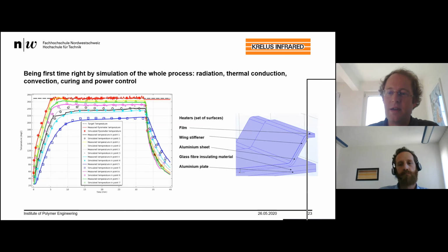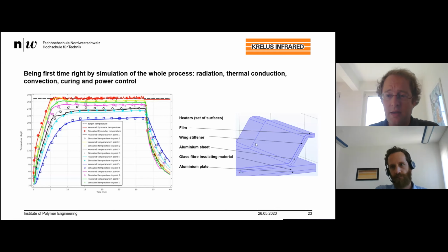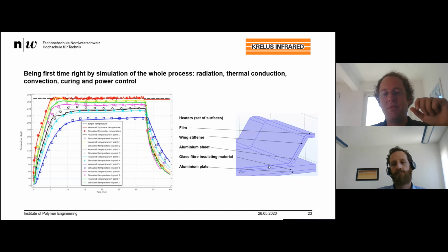And there's a kind of trick which we apply. So we have, of course, a vacuum setup, then the composite part, then we have our mold, and then we apply a kind of insulation system below our mold to avoid huge heat loss through the thickness. So on one hand, we need a small heat flow through the part to be able to avoid the exothermal reaction. But at the same time, we can modify this insulation material to decrease the gradient in the part itself.